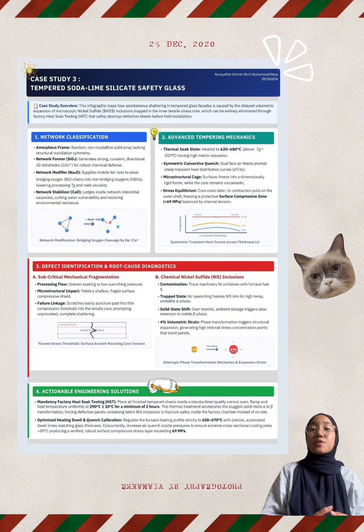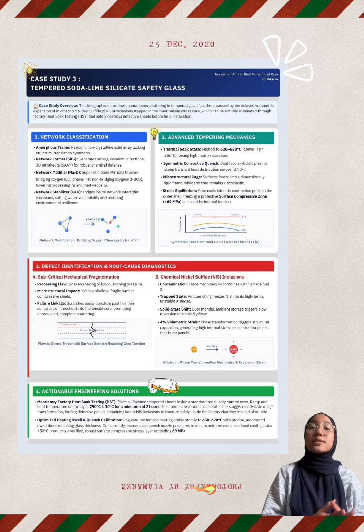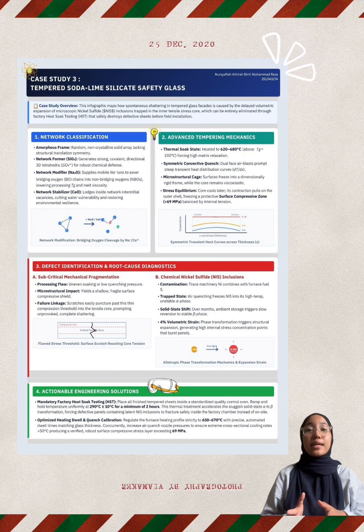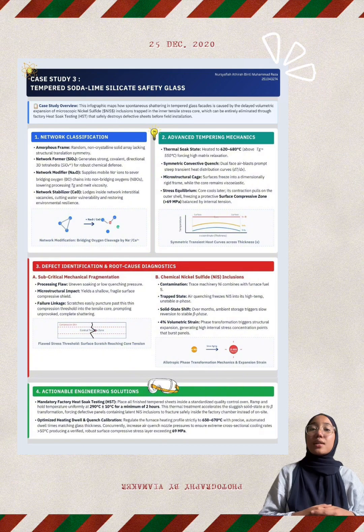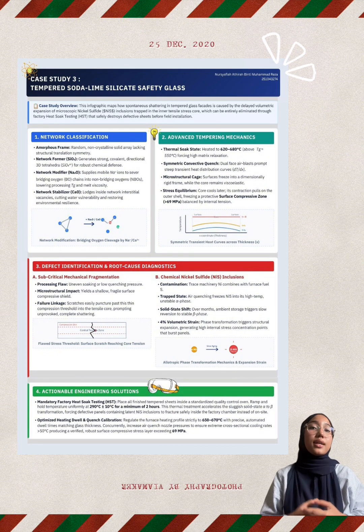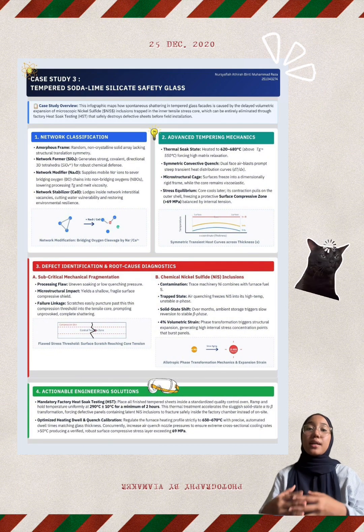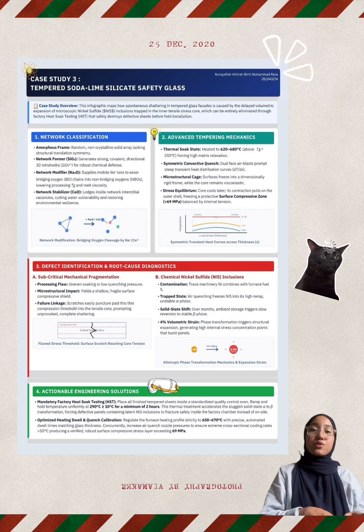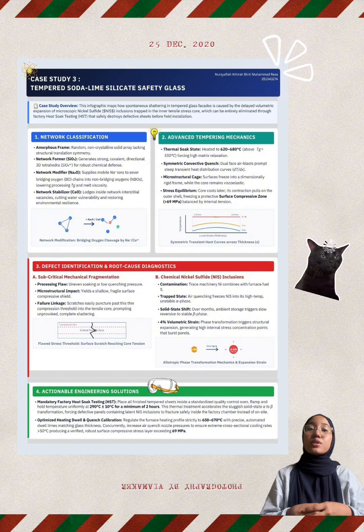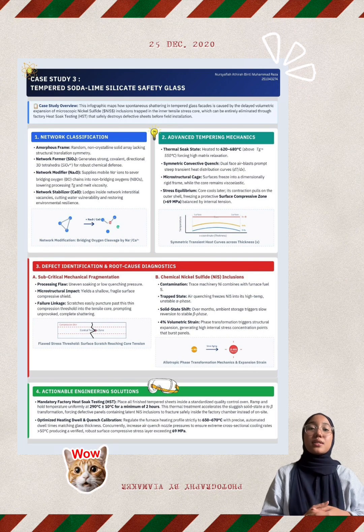To give this glass its strength, we use advanced tempering mechanics. We heat the glass to a thermal soak state between 620 degrees Celsius and 680 degrees Celsius, well above its glass transition temperature. Then, we hit it with a symmetric convective quench, a rapid air blast on both surfaces. The surfaces freeze instantly into a rigid microstructure, while the inner core cools much slower. As that inner core eventually contracts, it pulls on the outer shell, freezing in a protective surface compressive zone exceeding 69 megapascals, which is perfectly balanced by internal tension.